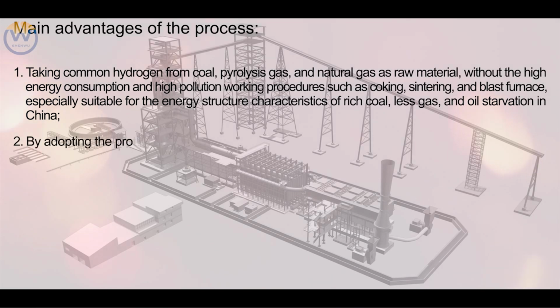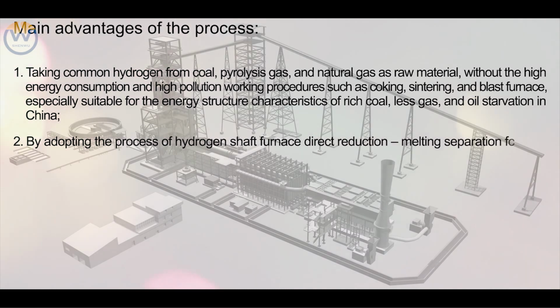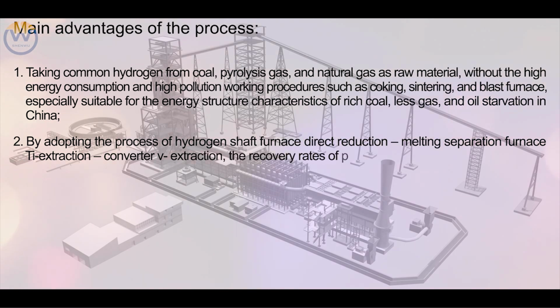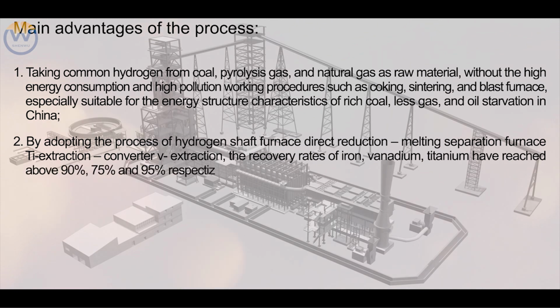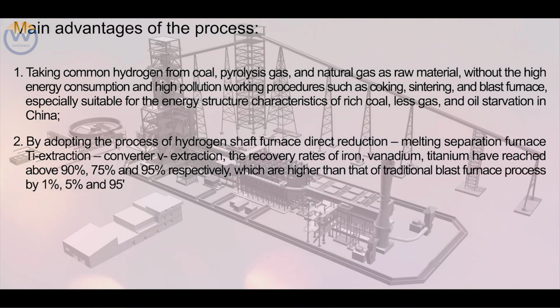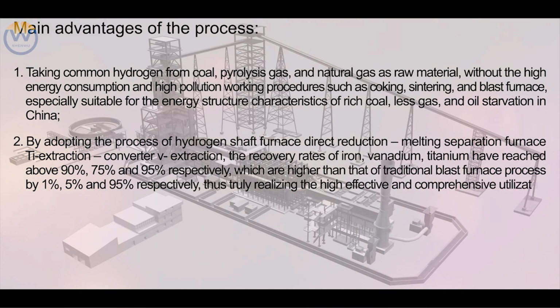2. By adopting the process of hydrogen shaft furnace direct reduction, melting separation furnace Ti extraction, and converter V extraction, the recovery rates of iron, vanadium, and titanium have reached above 90%, 75%, and 95% respectively, which are higher than that of the traditional blast furnace process, thus truly realizing the highly effective comprehensive utilization of iron, vanadium, and titanium resources.